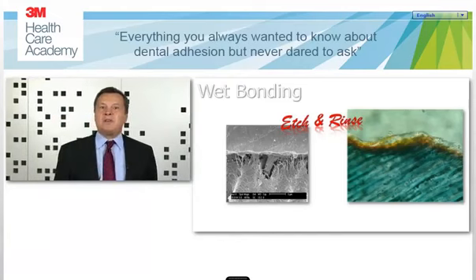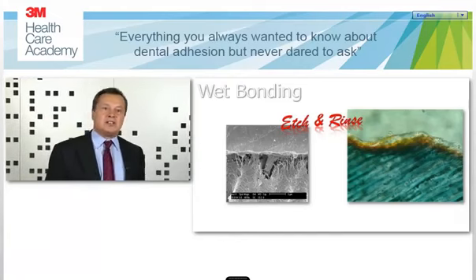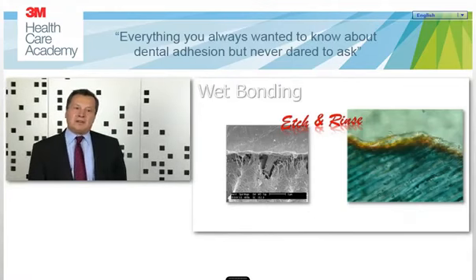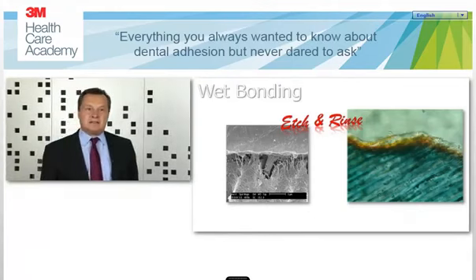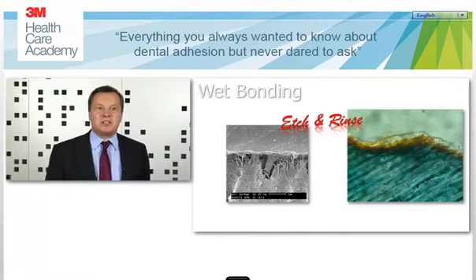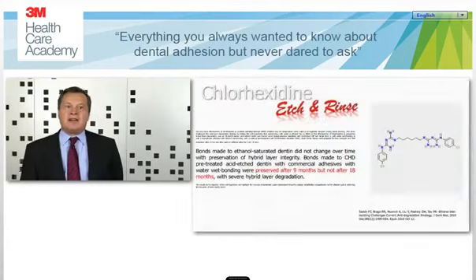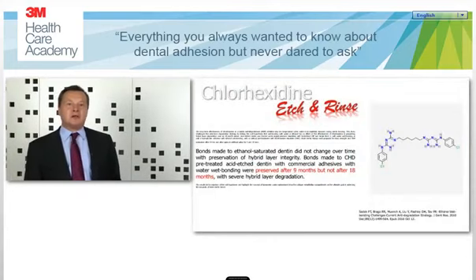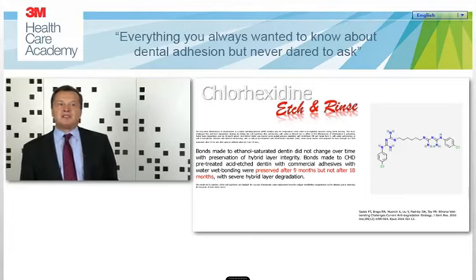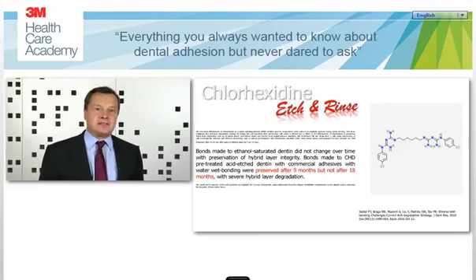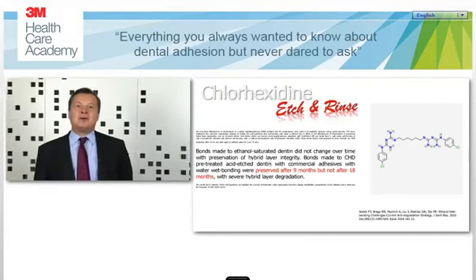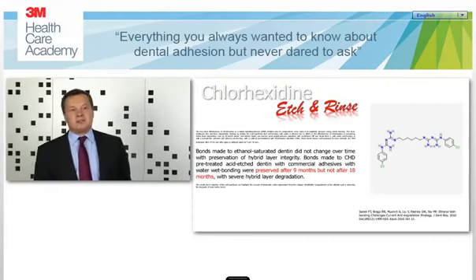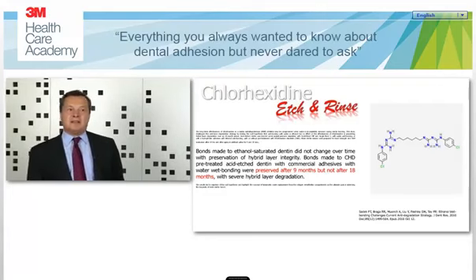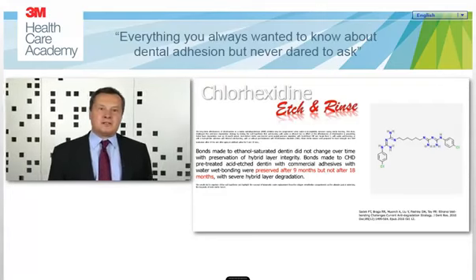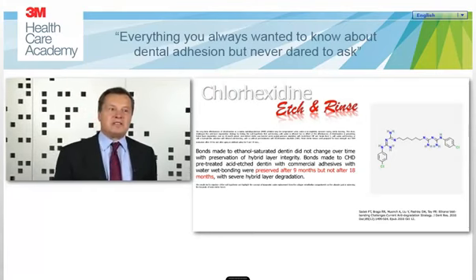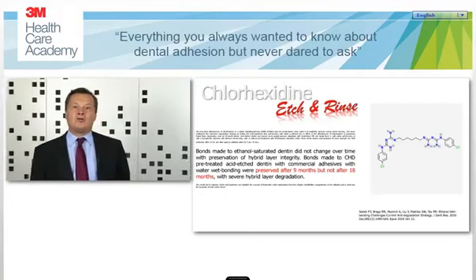And this is, of course, a weak zone of adhesion because this collagen can be attacked chemically or even biologically, can degrade, and in the end, the bond may fail, especially in the long term. There are some proposals in the literature on how this can be avoided. There is especially the recommendation to use chlorhexidine to impregnate these exposed collagen fibers and thus avoid this chemical or even biological disintegration. But unfortunately, this protection by chlorhexidine works most probably only in the short term, maybe some months, but not in the long term over years.